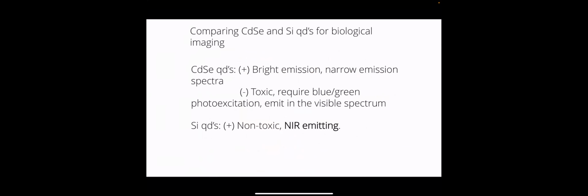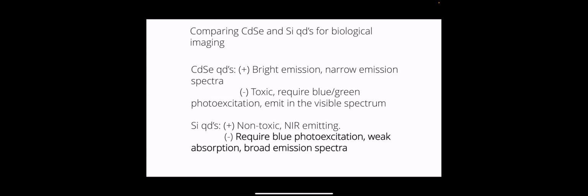And the reason is, well, one of the reasons is the silicon light emission is in this kind of optical window for biological tissue. So you have these windows of transparency for optical tissue and water. And so silicon emits in that range. What's shown here is a kind of NIR1 or near infrared 2 region, kind of in there. So that's interesting. There are other materials that can emit in that range, but cadmium selenide, which is one of the more common, commercially available fluorophores for biological imaging, doesn't emit in that range. So silicon emits in the near infrared, and it's also non-toxic, so it's biocompatible. And those are two positive things about silicon.